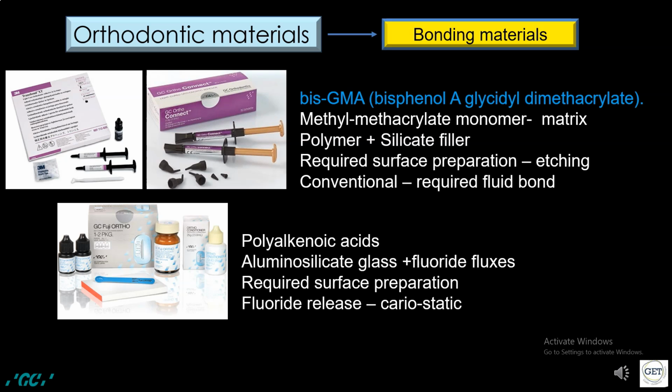The viscosity should be optimal to allow easy and stable attachment placement on the teeth surface. The bond to the tooth surface requires a surface preparation, using 37 percent phosphoric acid for mechanical bond to the tooth. No chemical bond is established.